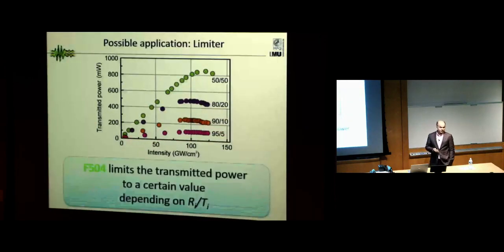And now a few words about an application for this effect. Consider you send the same intensity to the sample, and then you start changing the intensity. I mean, the intensity starts to fluctuate for any reason, to quite large values. What you see here is that as soon as the sample gets into the nonlinear regime, the sample starts to work like a limiter. Whatever intensity you send, the sample will not output more than some certain level. It means the transmission and reflection change in such a way that, at some energy, whatever more you send, the sample still transmits just some certain value of milliwatts. And you can observe this for any ratio when you adjust to a different ratio.